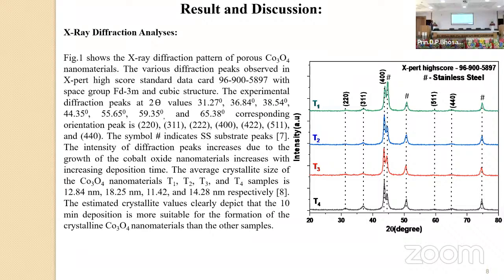I synthesize the material and then find out the results and discussion. First is XRD. XRD shows some peaks of the cobalt oxide material and the Fd3m space group of the material. It also shows hash peaks, that is the stainless steel peaks from the stainless steel substrate. This was optimized at various deposition times, that is 5 minute, 10 minute, 15 minute and 20 minute. The 10-minute deposition time shows a very good crystalline size of this material, and this shows the cubic structure of this material.